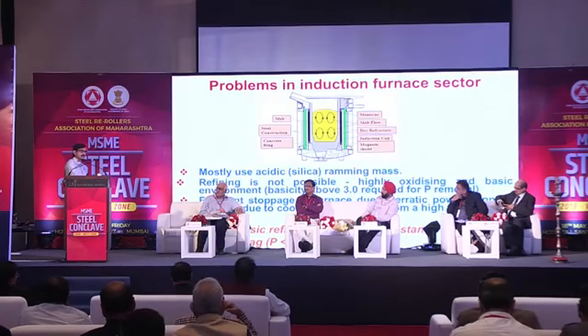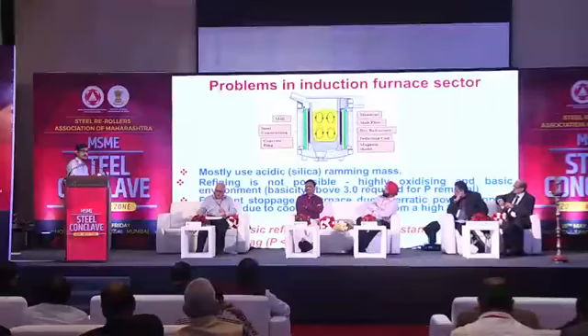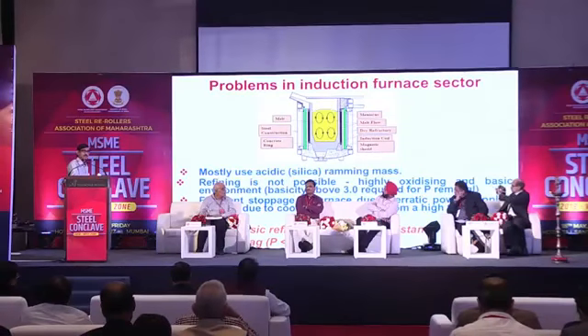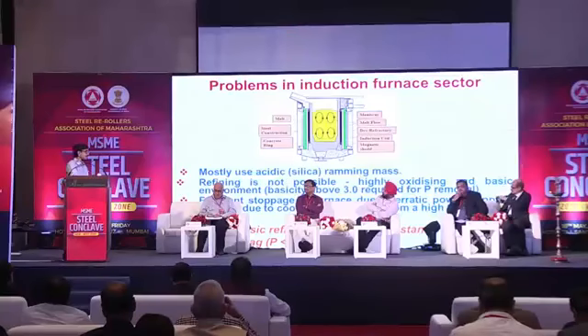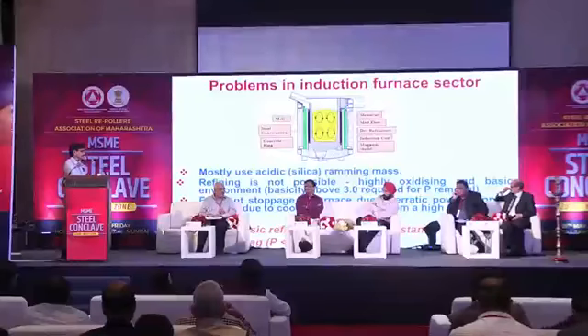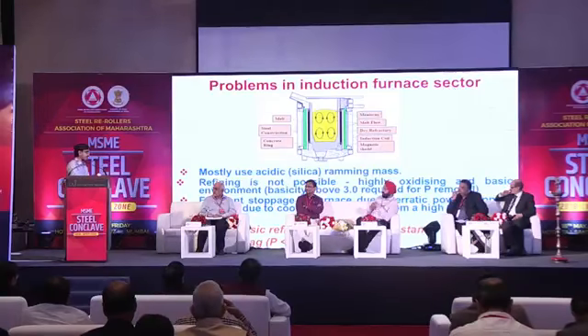Right now the induction furnace mostly uses acidic ramming mass, and if you need good quality steel, you have to remove the phosphorus, and to remove the phosphorus level below 0.05%, the slag basicity should be very high. Whatever flux you use also contains a considerable amount of alkali or alkaline earth metal. So the slag basicity should be high, and the presently used silica ramming mass cannot withstand the severe refining action. So our target is to develop a ramming mass that may be neutral or basic.